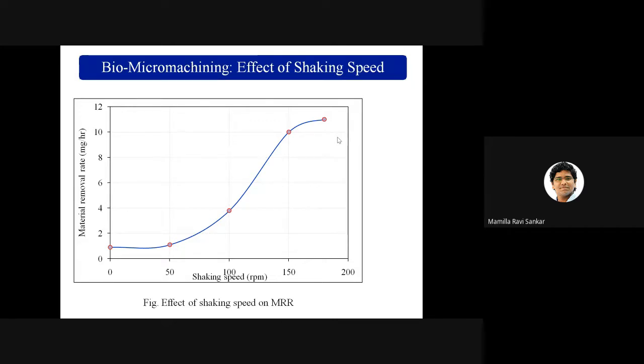Regarding shaking speed, you can have the sample on a shaker, but in this condition we have not used any shaker. We kept static conditions at first, and later we moved to some RPMs. As the shaking speed increases, the material removal increases because of the dynamics. At the same time, the advantage we have seen is that partially attached atoms are removed by the dynamics of the liquid when you increase the RPM, which helps the organisms to interact with the next atoms.